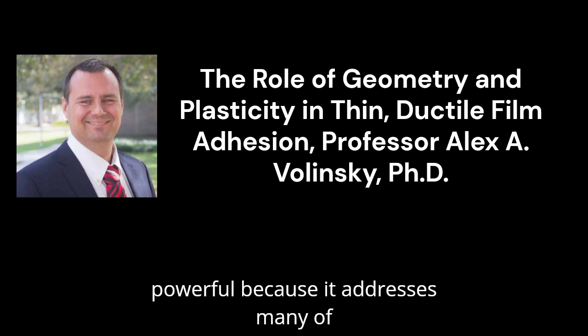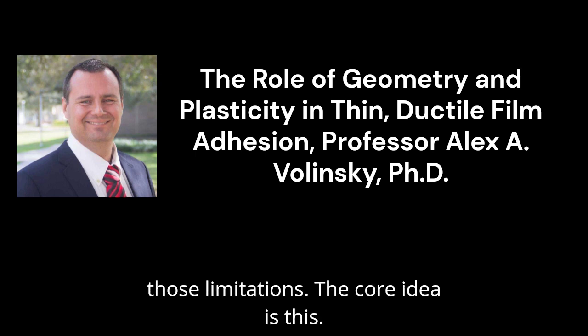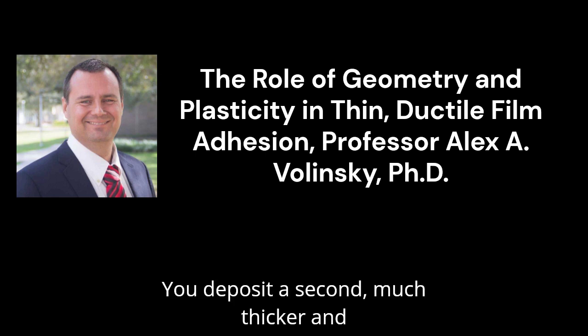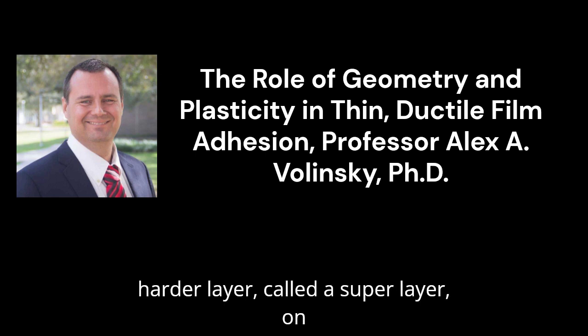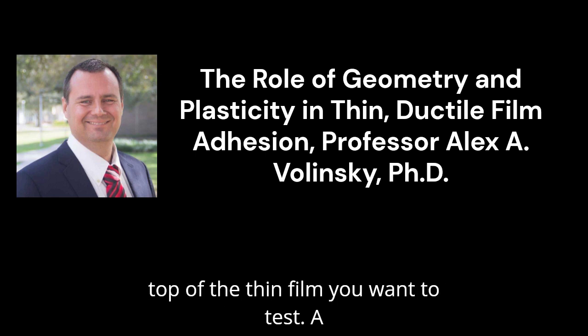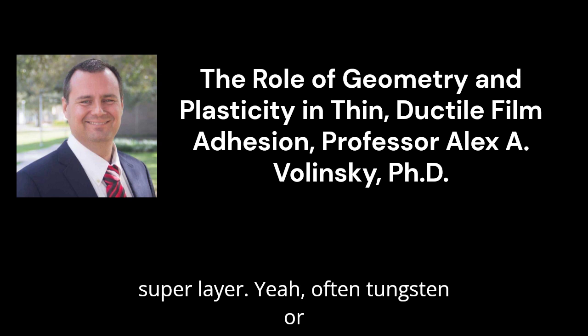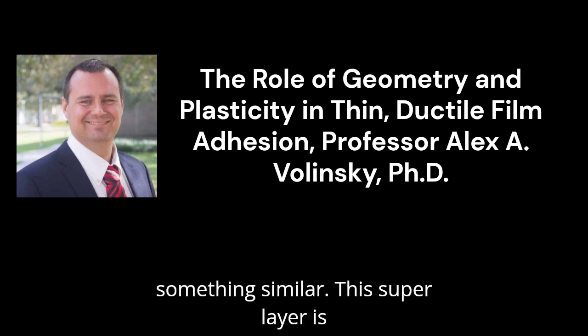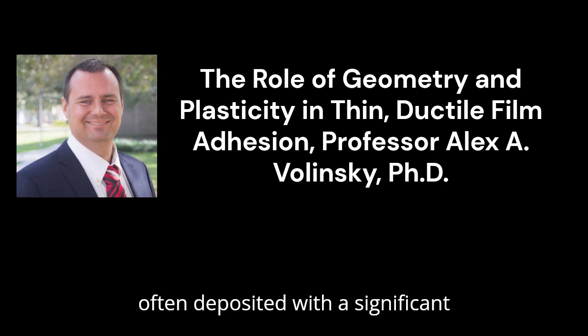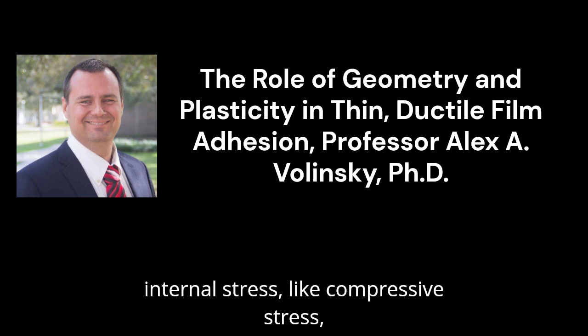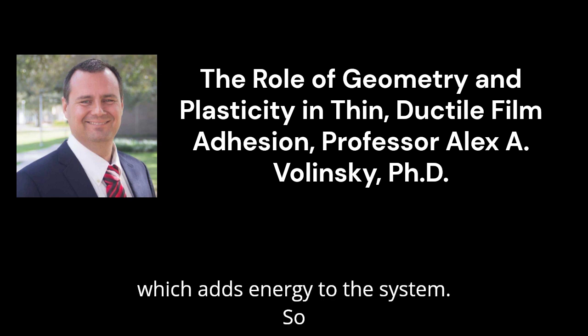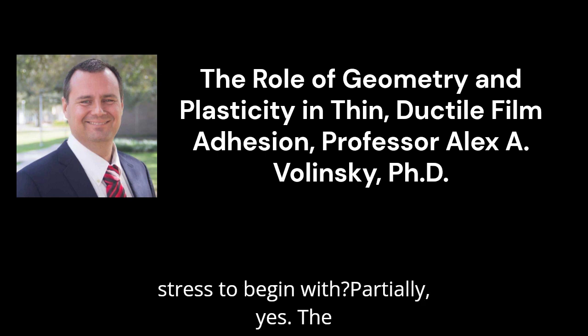This test is quite powerful because it addresses many of those limitations. The core idea is this. You deposit a second, much thicker and harder layer, called a superlayer, on top of the thin film you want to test. A superlayer. Yeah, often tungsten or something similar. This superlayer is often deposited with a significant internal stress, like compressive stress, which adds energy to the system.